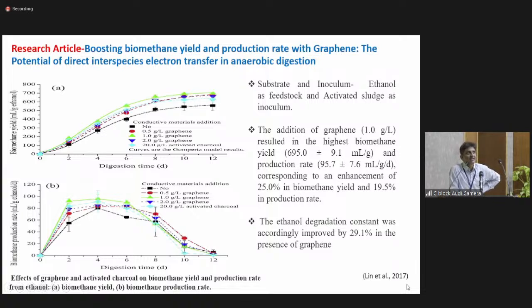This study is basically on the generation of biomethane with graphene nanoparticles. In this study, they took different types of graphene at different concentrations, like 0.5, 1, and 2 grams per liter, and another one with activated charcoal. They found that the reactor with a concentration of 1 gram per liter generated nearly 25% more biomethane.